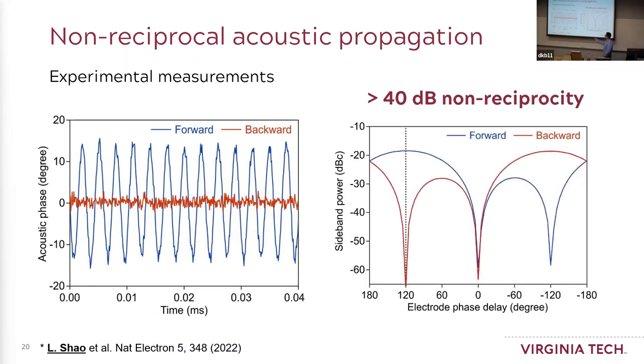That's in the time domain. If you look at how we can change the phase difference between each electrode, then we can be configurable for sure. If you change the phase relationship between the electrodes, you can program which direction you want to modulate, or do the reverse way. And by comparing the sideband signal, we can define the non-reciprocity, which here is over 40 dB, which is a pretty decent number. Although this is not for the isolation yet, this is just for the non-reciprocity. Yeah. This is about the electro-optical modulation.